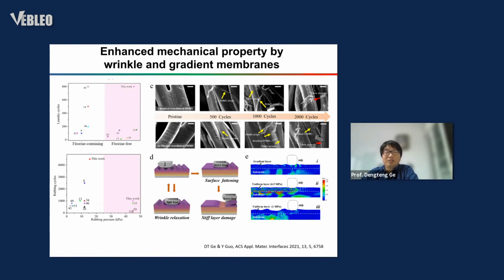One is the wrinkle. The wrinkle can be flattened and recover. Another one is the gradient membrane. From the simulation, we can find that if the coating is a gradient, the stress is not very high. It is the lowest compared to the uniform coating, even when the coating modulus is high on the lower modulus side. So, thanks to these two parts, the fabric can withstand very high laundering cycles.